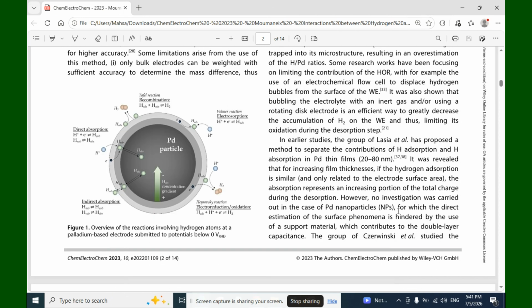In earlier studies, the group of Lasia and his colleagues proposed a method to separate the contributions of hydrogen adsorption and hydrogen absorption in palladium thin films between 20 and 80 nanometers. It was revealed that for increasing film thickness, if the hydrogen adsorption is similar and only related to the electrode surface area, the absorption represents an increasing portion of the total charge during the desorption.